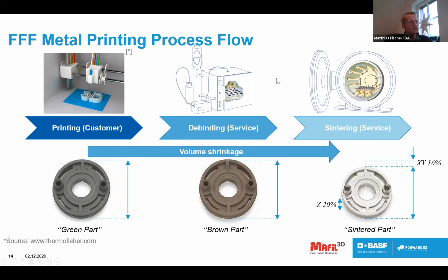Concerning or in between those steps, debinding and sintering, the parts get very brittle because the polymer matrix, the strong material in between, is gone. After the sintering process, you have a final metal part.